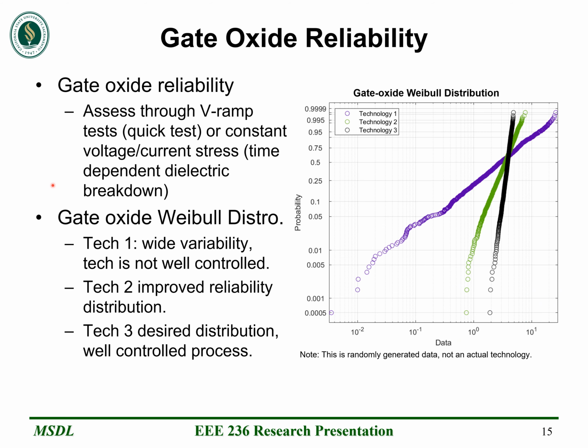So how do we assess gate oxide reliability in general? Well, there's a couple different methods you can use. The first method, which is a very quick test, is a V-ramp test. During this test, you apply a voltage on the gate of a MOSFET or on a capacitor structure and monitor the leakage current through the gate oxide. Then as you ramp the voltage higher and higher, eventually you'll see a spike in the leakage current, and this is an indication that your oxide has broken down completely and has resulted in a short circuit.